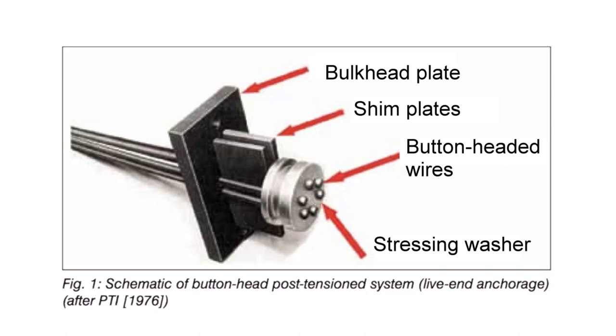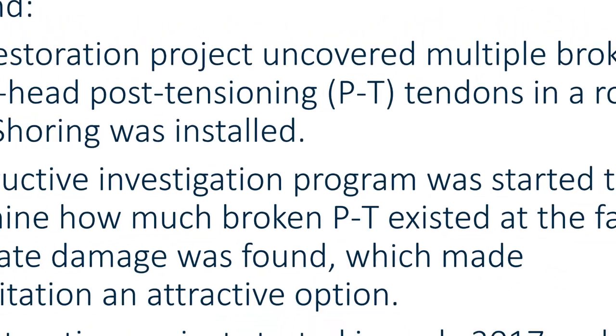So what happened with a lot of these systems was, as this would crack over time and water would get into the system, you have just basically uncoated steel that's just open for corrosion. Since this is high strength steel, the corrosion mechanism is pitting rather than corroding and blowing up, expanding exponentially. So you get pitting, and as soon as the pitting is so severe, these wires are going to start popping. And then the other thing too is to lock this thing off, you essentially stretch this thing to the manufacturer's required elongation, and then you put shims in here to shim in between this head and the compression plate in the concrete. And then once that's done, you release your jack, the tension stays on this, and then you encase this whole thing in concrete. So that's how this system worked.